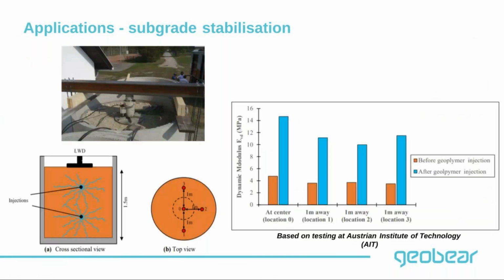We've carried out some tests in Austria where we had a testing pit, and we filled it up with very soft soil that has a modulus of roughly 4 MPa, and we introduced our injections to that soil. What we did was measure the stiffness before and after using an LWD. And this is what the results show on the chart on the right-hand side.